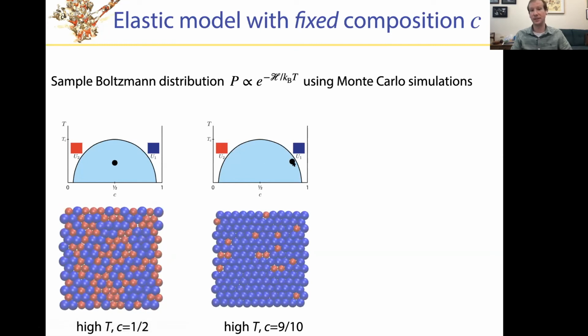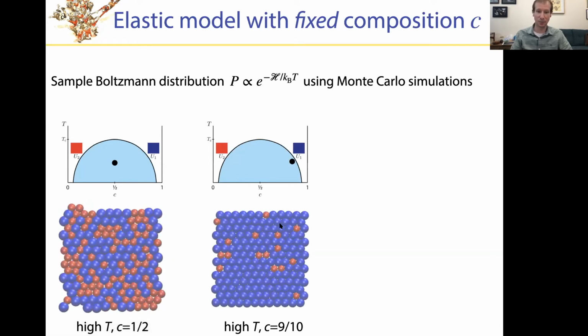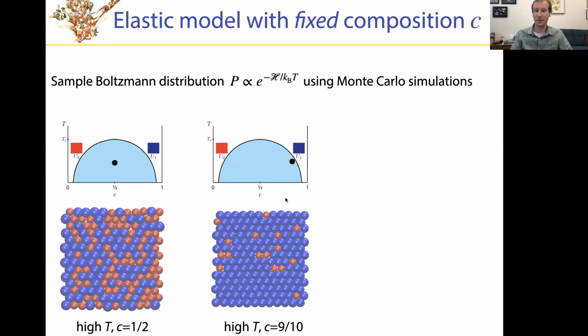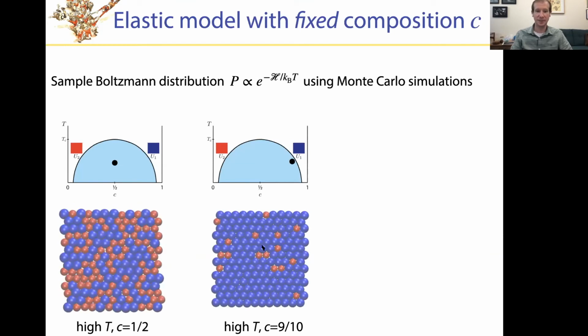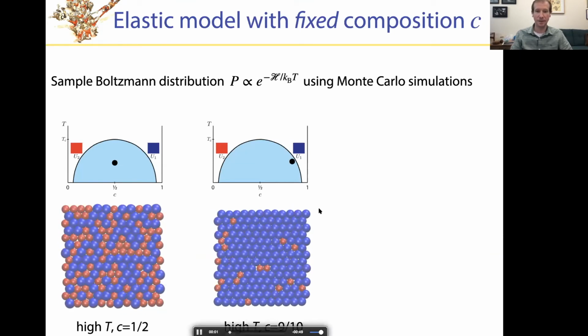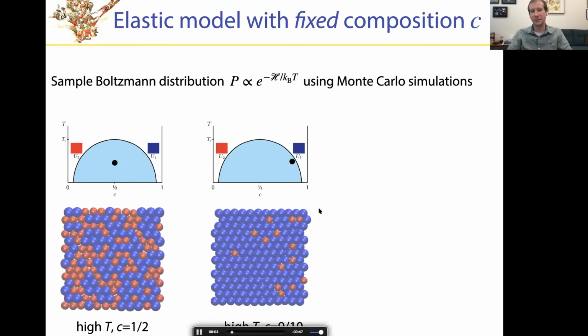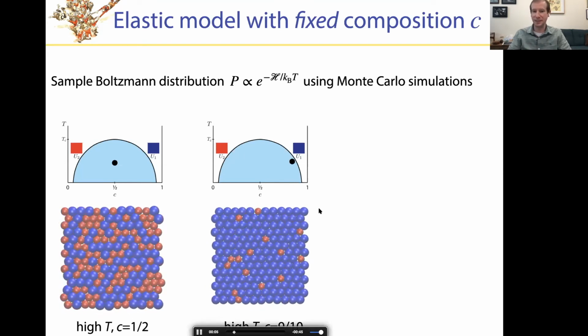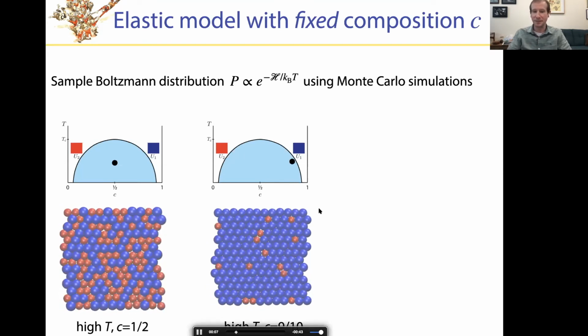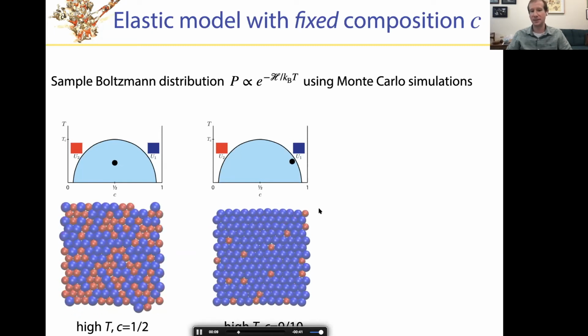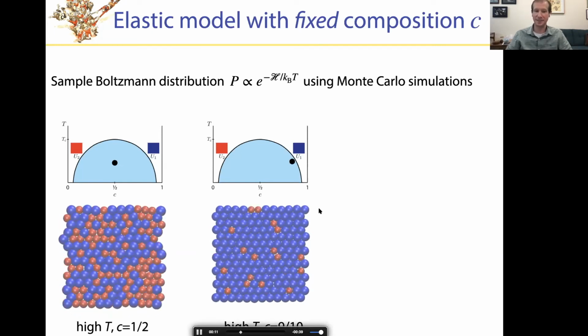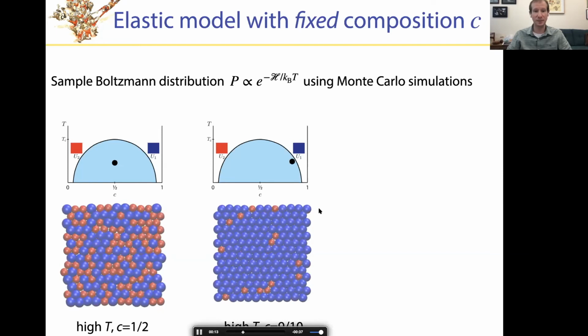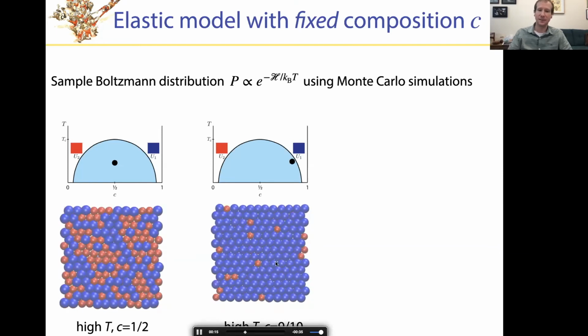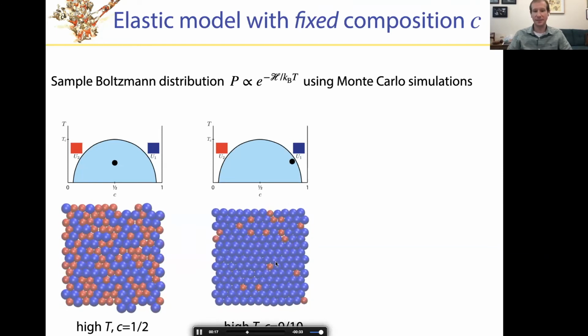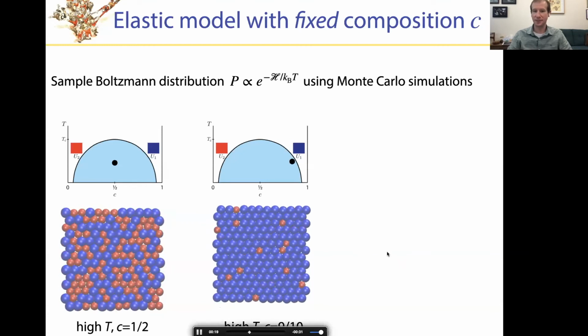So maybe we're just in the wrong part of the phase diagram. So let's move over here to a composition that has more blue particles and fewer red particles and see what happens there. And now we find curiously that the red things don't even seem to want to stick to each other. Even though macroscopically these materials want to be separated in the sense that the lowest energy state would be a pure material, there doesn't seem to be any tendency for these things to aggregate, which is really curious.